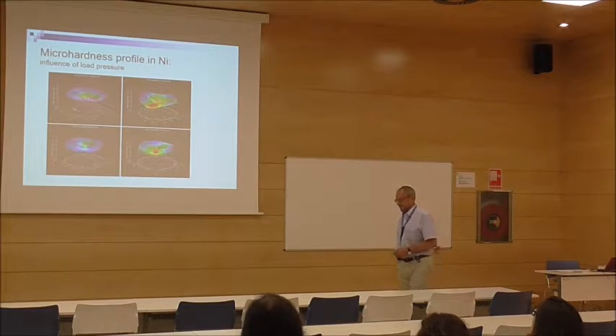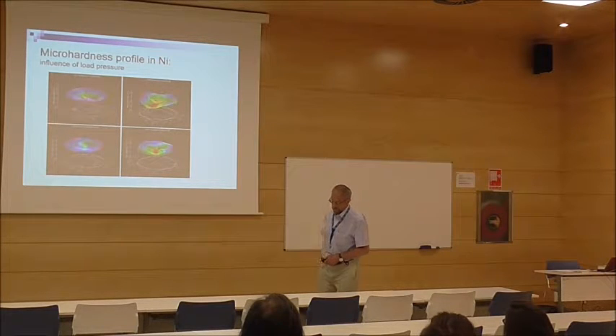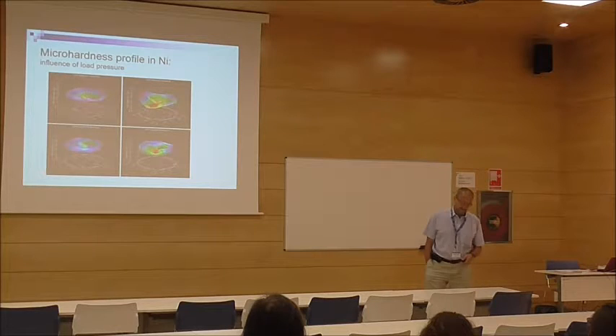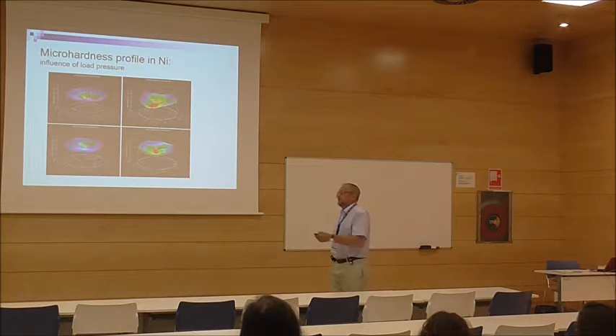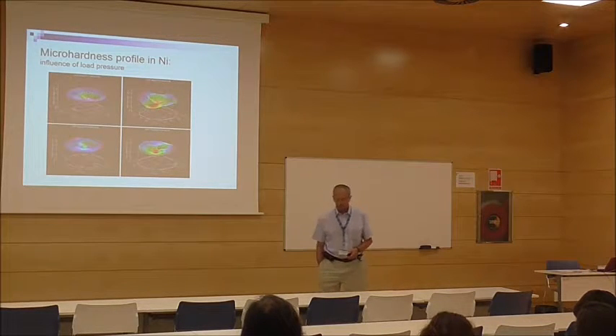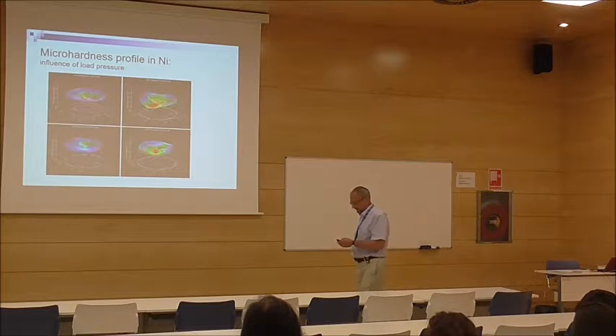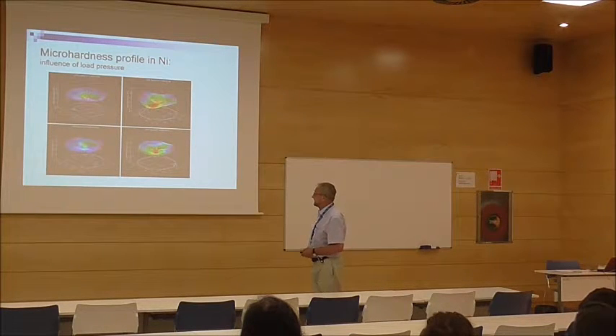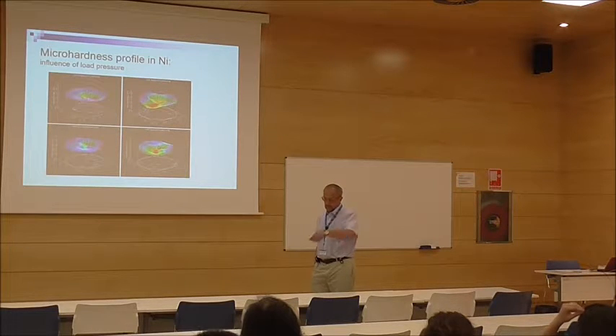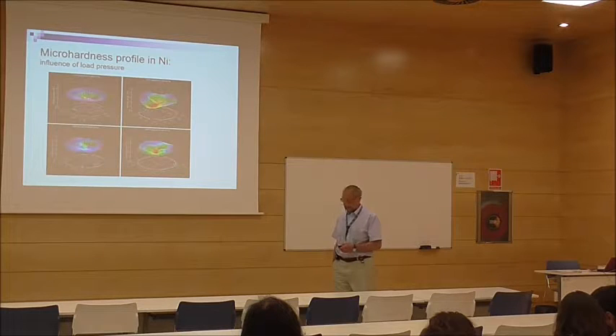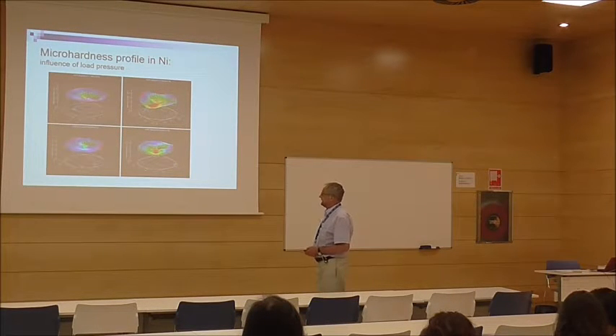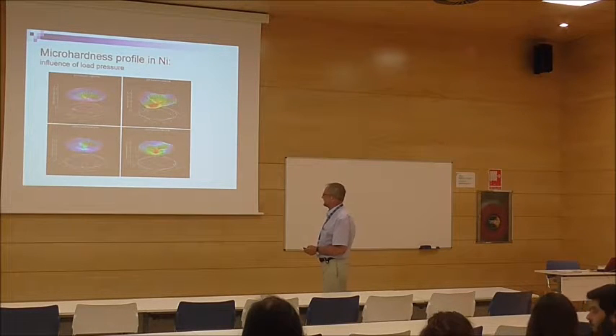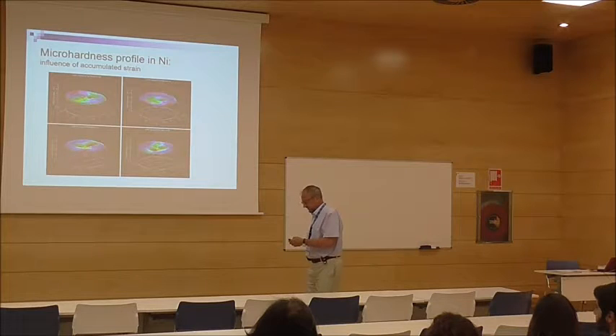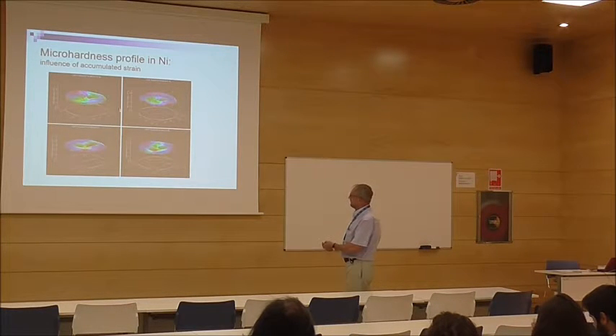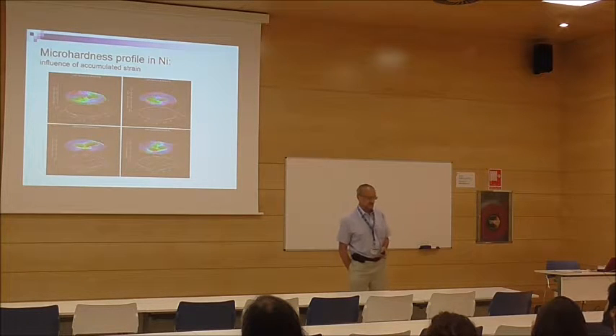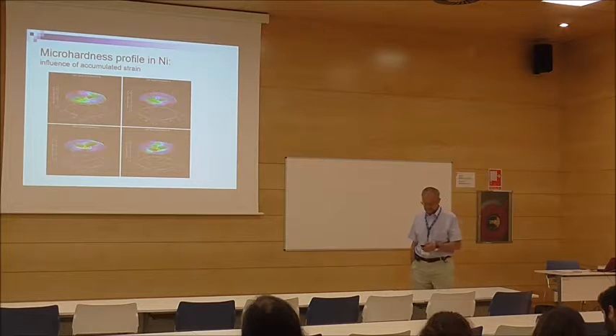And before that, everything published on HPT, the papers were saying that after 5 turns and under a pressure of 5 gigapascal, you can get a homogeneous distribution of hardness across the disk. But we did a very careful examination and found that there is still some profile of microhardness even at a pressure of 5 gigapascal and after 5 turns. So it depends on the number of rotations and load. So there is still some gap. You see there is still a gap. Not a small one. It's in the range of the error, but you can detect it.